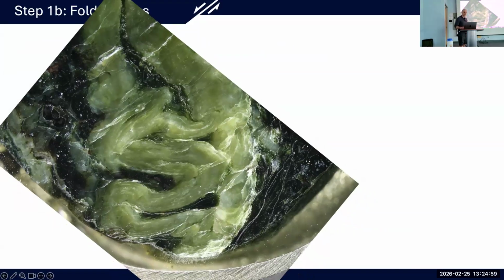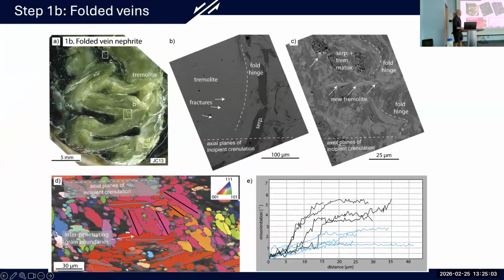If we take a closer look, you can see that the deformation and the change in shape can be quite intense. You can imagine that these veins may have once been straight and that they've been squished and compacted together. And if we take a close look at the fabric of those tremolite needles within it, we see that the needles are beginning to show signs of deformation, the very deformation that has accommodated this bending and folding of the veins. And they do so by the presence of interpenetrating grain boundaries. So our individual tremolite needles, as we see in this EBSD map, are penetrating into one another. And this is telling us an important clue about how this deformation took place.